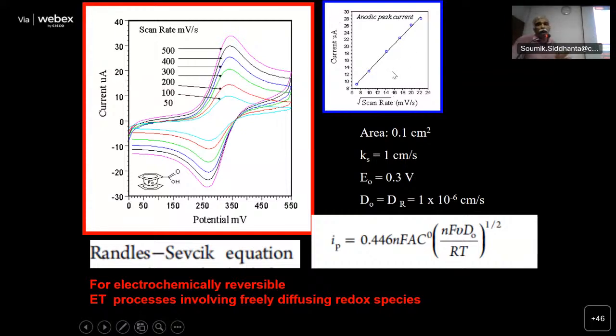That shows that you have essentially a reversible system, and you can calculate from this a diffusion coefficient. What is shown here is simulated with these numbers: area 0.1 centimeter square, rate constant 1 centimeter per second. That means a really reversible system and E naught value. You can apply the Randles-Sevcik equation. It tells you IP is proportional to these parameters.